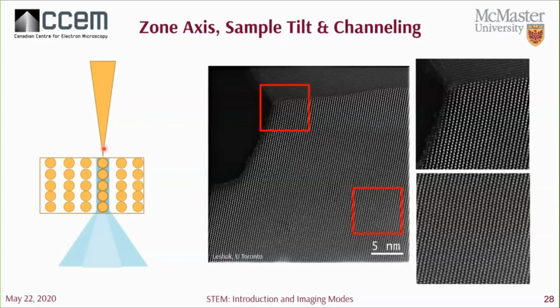It's important to note that the strongest contribution comes mostly from the atoms positioned closest to the beam, say these atoms here. And then as the probe travels, the electrons travel through your sample, the probe is depleted, and when it reaches the atoms in the lower column, it's scattered in different directions. Therefore, if you have a thick sample or a region where it's a little off axis, you'll see some background contribution between the columns of atoms. Here, showed here, a little part of this sample is a little bit off axis, and so you see more background as opposed to this region of the sample where you have a good on axis orientation, so you get a good contrast.